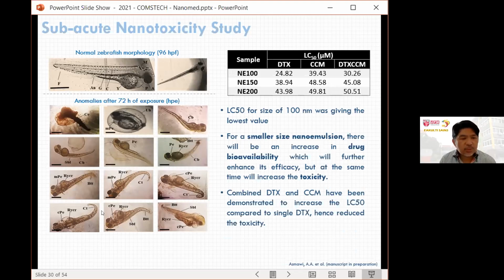Therefore, we can see that the scoring for the acute toxicity, assessed with regard to the survival and morphological changes, is as depicted here. We are looking at the LC, the lethal concentration value for each nanoemulsion sample. Again, we can prove that the size of 100 nanometer gives the lowest value compared to the other sizes. Besides that, the combined DTX and CCM have also demonstrated to increase the LC50 compared to single DTX. So these results were in line with our previous in vitro and ex vivo nanotoxicity studies.